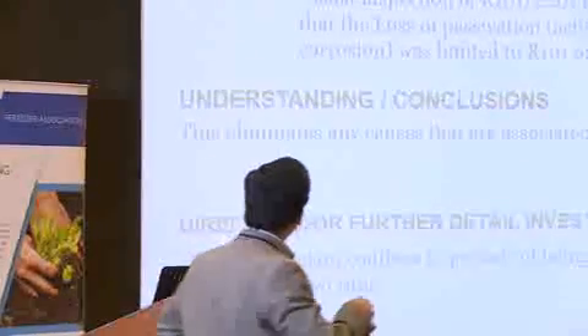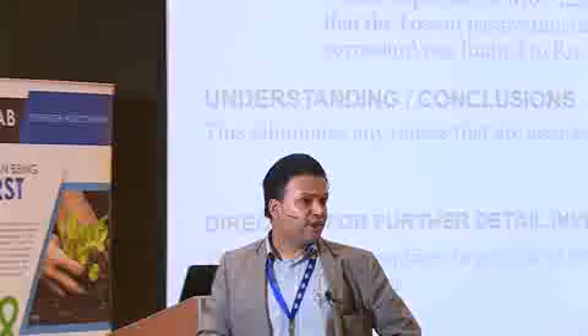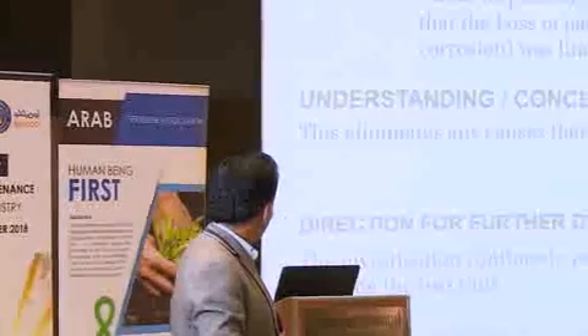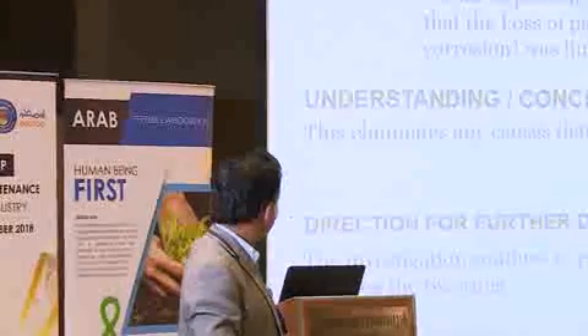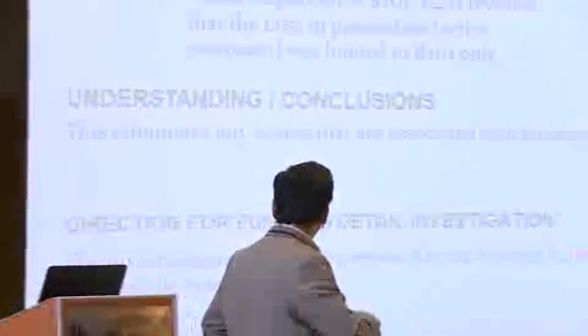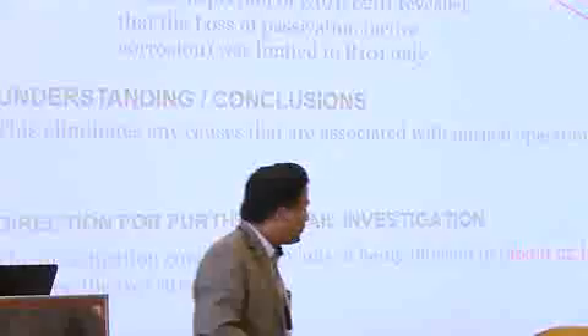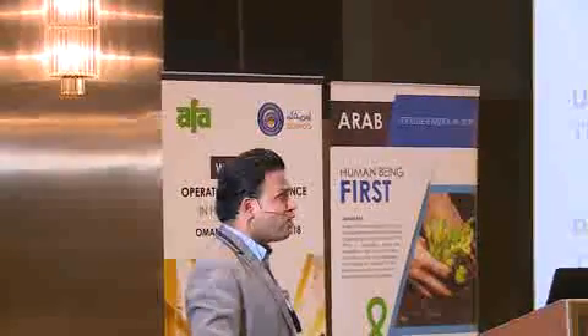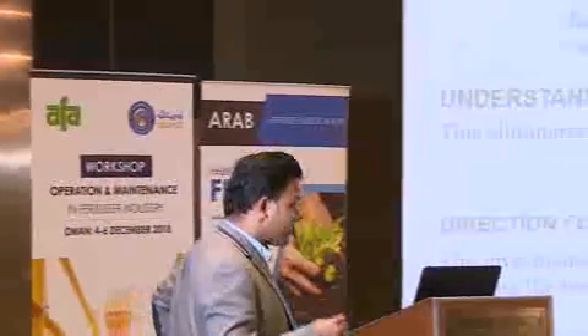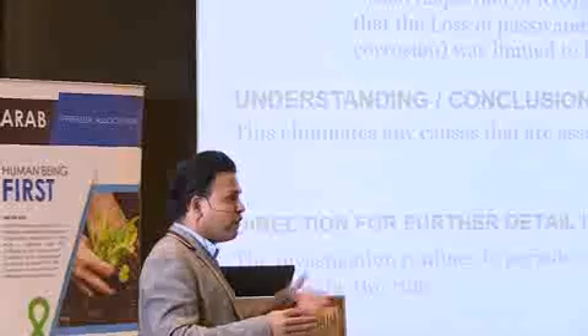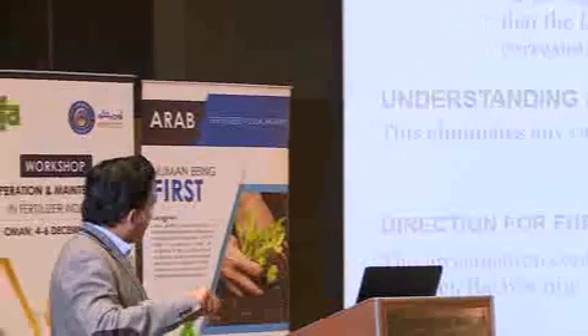To look at the other equipment, they also opened the stripper. There they did not find any active corrosion, so the equipment was intact. The layer was intact, as it should be. So to do the further investigation, they concluded that something must have occurred during the block-in period. The block-in period was 22 hours with this material, 316L urea grade. The maximum allowed is 72 hours, as presented. So this 22 hours was the time to look at what went wrong.